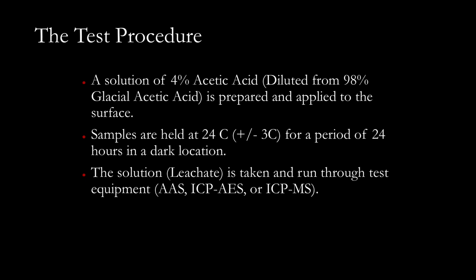That acid is then placed on a tile or in a bowl with a plasticine wall built up around it. You measure the surface area of the tile you're testing or the bowl and the volume of liquid that you're actually using. The solution is left to sit for a period of 24 hours at approximately 24 degrees centigrade, plus or minus 3 degrees. It's a little hard to keep it at a constant temperature. This allows for a process called ion exchange to occur, where the hydrogen in the acetic acid can replace itself with a portion of the glaze surface, either the fluxes, the silica, the copper, what have you.